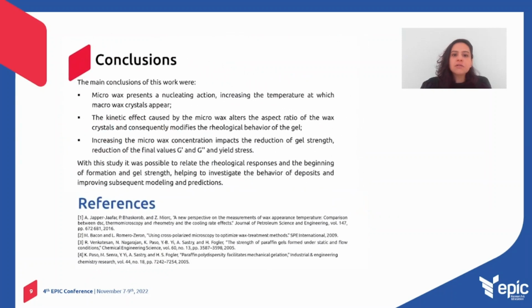To finalize, the conclusions of this work: the micro wax presents a nucleation action, increasing the temperature at which macro crystals appear. Also, the kinetic effect caused by the micro wax interferes with the aspect ratio of the wax crystals and consequently modifies the rheological behavior of the gel.